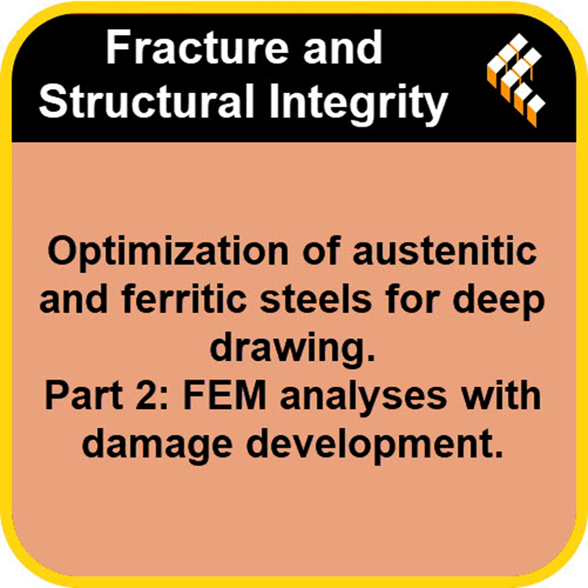Everything changes. With low friction, the material flows easily from the flange into the die. The strain map smooths out completely into a single bell shape. Meaning the strain just increases smoothly towards the very center. Exactly. Maximum strain, maximum stress, and the eventual failure point all shift to the apex of the spherical cap, right at the very bottom of the cup where the punch nose is. Wow, completely different location, and the deformation mode there? It becomes primarily balanced biaxial stretching. The material is being stretched fairly evenly in all directions across the plane at the bottom of the cup.